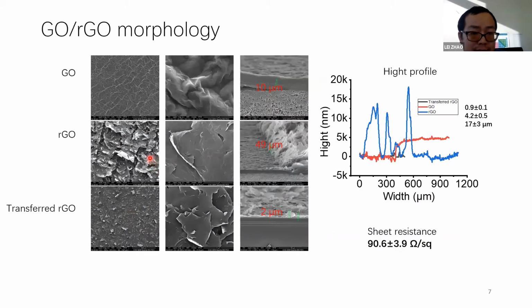We first characterize the morphology of the materials. As you can see here, from the SEM picture, the graphene oxide film is quite homogeneous with a thickness around 10 micrometers. Then after applying the laser, a foam-like structure was formed with a thickness around 15 micrometers. After we transfer it to a different substrate, the film still keeps a porous structure with a much smaller thickness. This trend was also confirmed by the height profile meter.